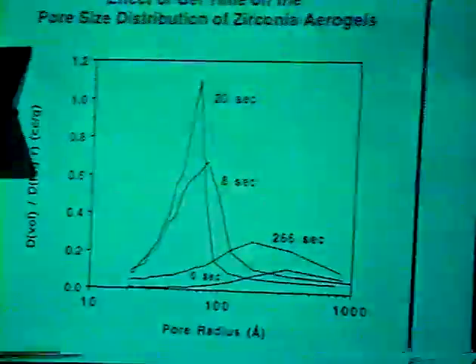And here, in addition to the surface area, I'm also showing you the pore volume variation as a function of gel time. Now, from this point on, all the samples I'm going to show you are synthesized using a water to zirconium ratio of 2. And as you can see, as we vary the gel time, the surface area goes to a maximum. So does the corresponding pore volume, and the variation is indeed significant.